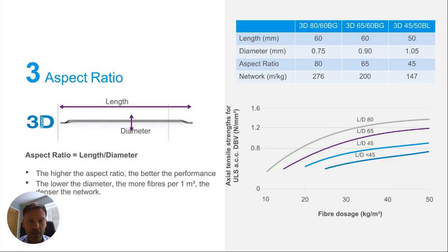If we have a 60 mm long fibre, drawn down to 0.75 mm diameter, what you actually get is a lot more fibres per kilo, which means you have a much denser network of steel inside your concrete. And you can see the actual network of wire you have in a cubic meter of concrete, if you look at the last row on that table, is twice that of the 4550.